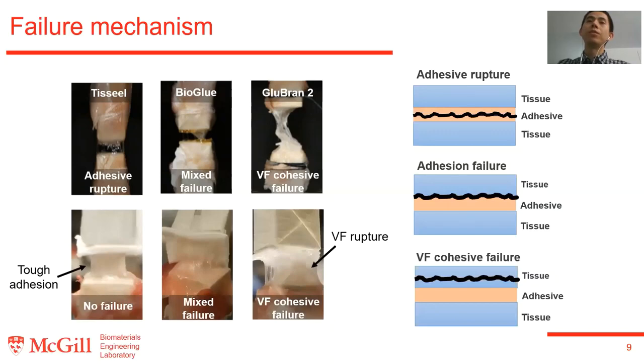And when we look at the images of the adhesion between our porous adhesive and the vocal fold, you can see that the adhesion is strong and tough before the failure occurs. The deformation mainly comes from the stretching of the adhesive itself. We have also observed that both mixed failure and cohesive failure of the vocal fold happened, which means our adhesive can provide enough adhesion at least comparable to the toughness of the vocal fold tissues. Our adhesive can also show a better performance compared to the GluBran 2.